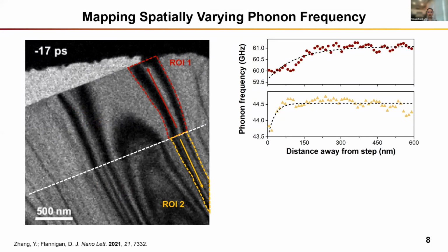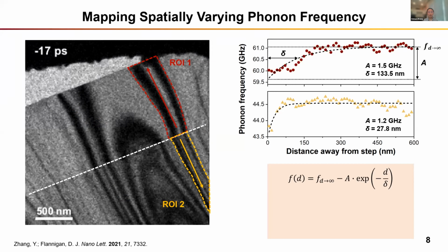And now we can repeat this process for a series of positions along the bend contour and look at the spatial distribution of the phonon frequency. So we can see the frequency rapidly increases as we move away from the step edge, and it plateaus to some bulk frequency value. We can fit this position-dependent frequency to an upward exponential decay function here, and then obtain a frequency reduction between 1 to 2 gigahertz. And this is essentially step edge-induced phonon softening.